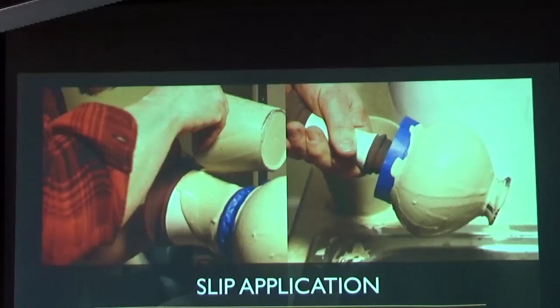Where it's thinner, it's going to crack in a much more fine network of cracks, and it's going to appear darker. Where it's thick, it might crack larger, but then you run the risk of it falling off in the kiln. I've had pieces where pretty much all the slip has just fallen off in the kiln. I'm watching it, and it's just raining down off the piece. And I'm going, okay, well, once that goes into the combustibles, it's just going to be plain black, and that's not exciting for what I want them to be.